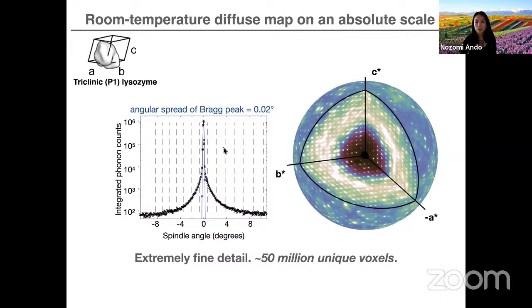So this is just to show how finely sampled the data could be. And the Bragg peaks for this particular crystal form are very sharp, so an angular spread or mosaicity of only 0.02 degrees. And we could separate it from all of these nearby scattering features as well. And because of that fine detail, we have many, many unique observations, 50 million voxels in this map right here.